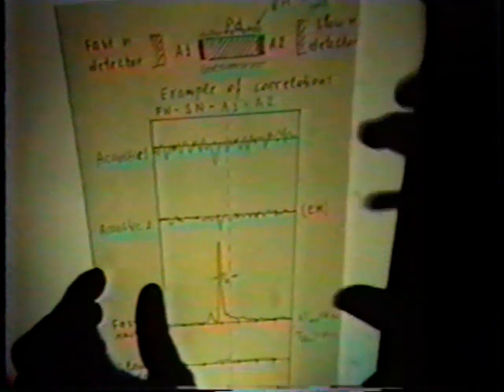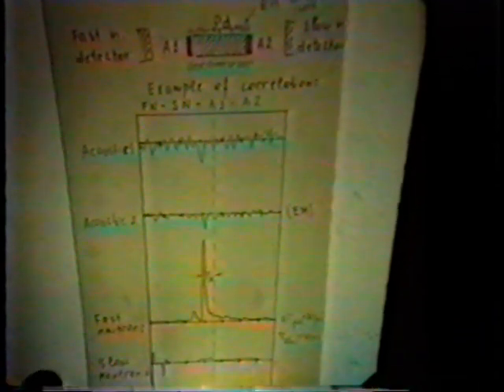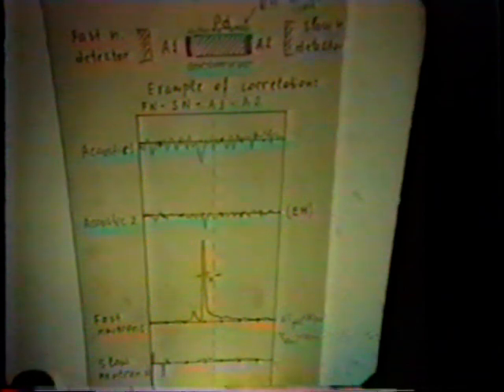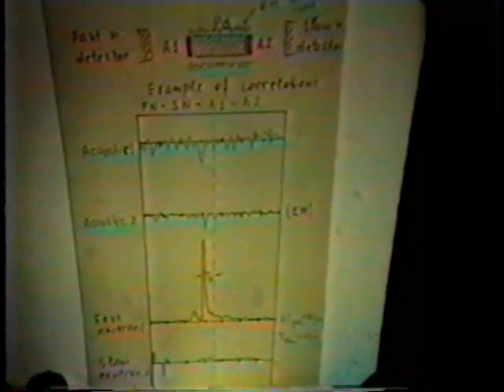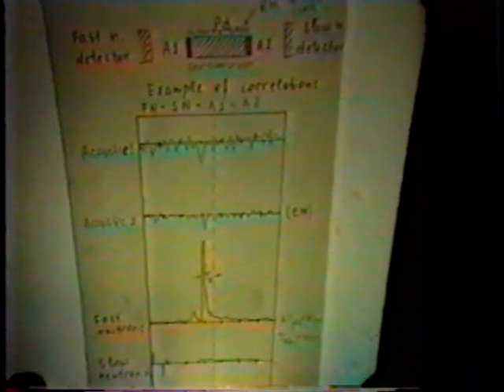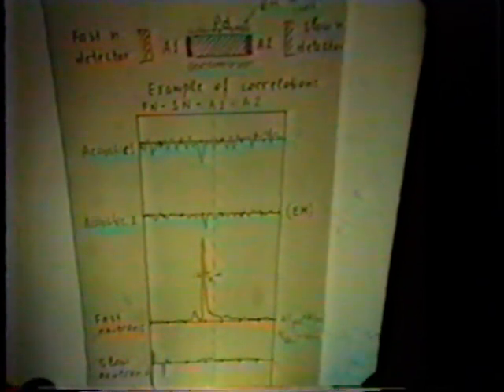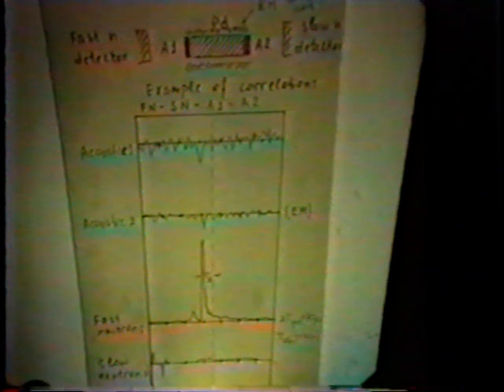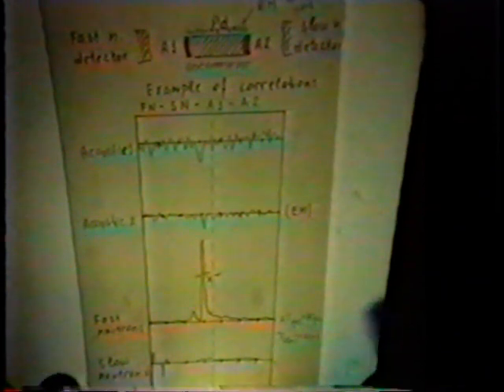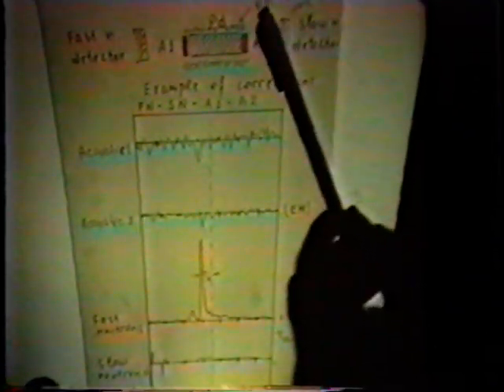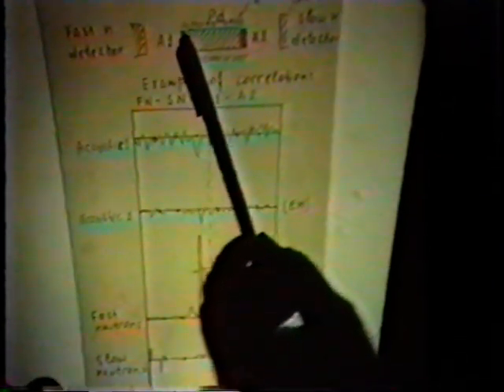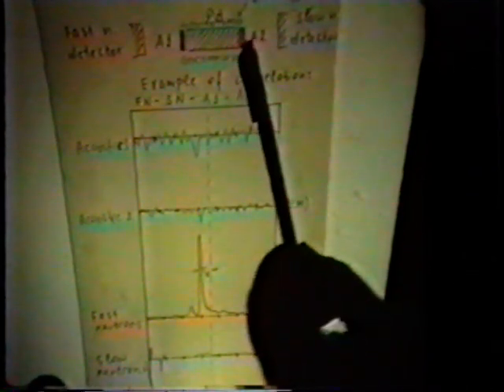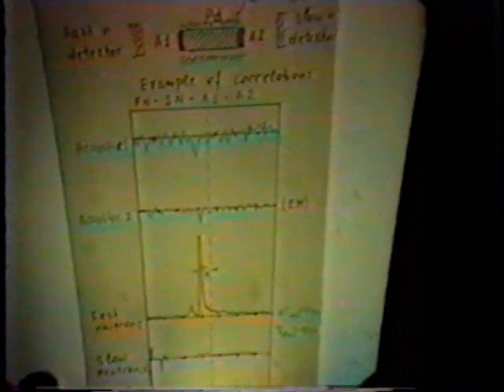Recently, the same group obtained some new preliminary data on correlation measurements. And I'll present results of only 30% which were analyzed. In general, in these new experiments, the group could measure 5 signals: from fast neutrons, from slow neutrons, from electromagnetic signals, and from two piezoceramic chips attached to the opposite ends of palladium cathodes.